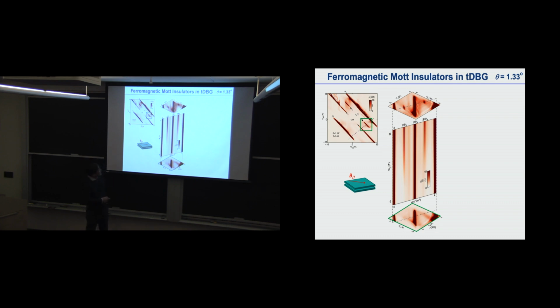What you see here is when you apply the in-plane magnetic field and increase it, tracing this half-filled gap level, it actually becomes much larger than what we started with, indicating it has become stronger. More exciting is that even quarter-filling states, which were missing at zero magnetic field, start to appear. This indicates that some spin structures can be reinforced under the in-plane magnetic field.